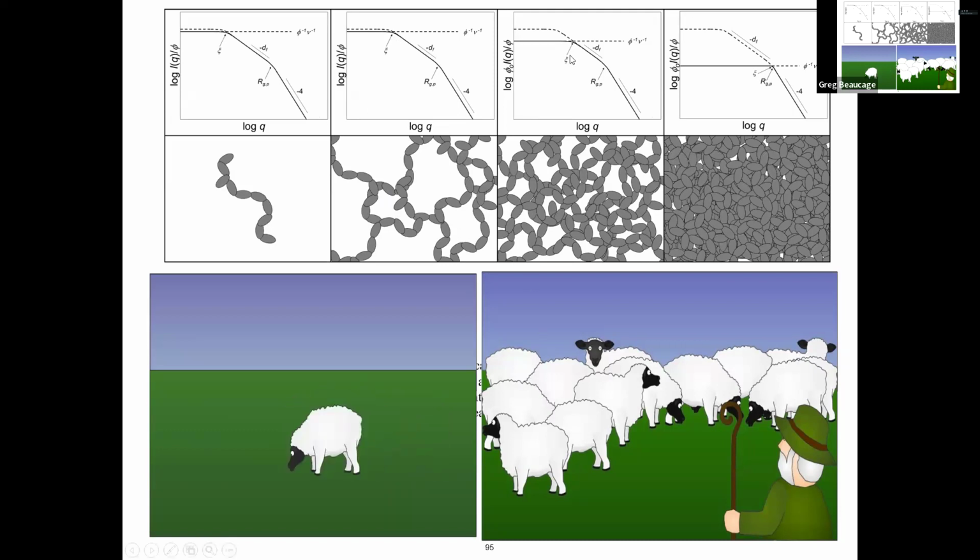Okay, so as the concentration increases, that correlation length, that hole size, gets smaller. So this thing moves over to the right in 1 over size. Eventually you get to just the objects themselves. You can't get any more information there, because they're packed. These are 3D objects, so they would pack solidly at that point. You can get the size of those objects, but that's it. So that's kind of what happens. This assumes that as these things are being packed together, they don't form a crystal.